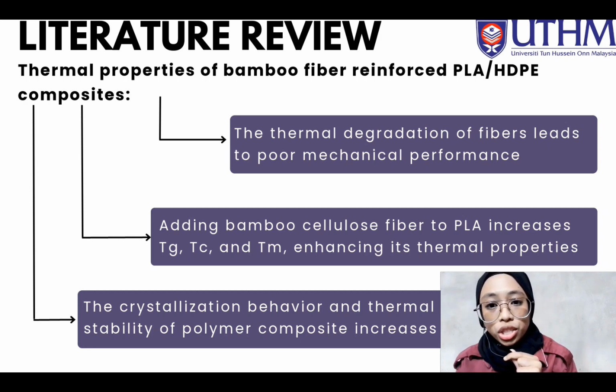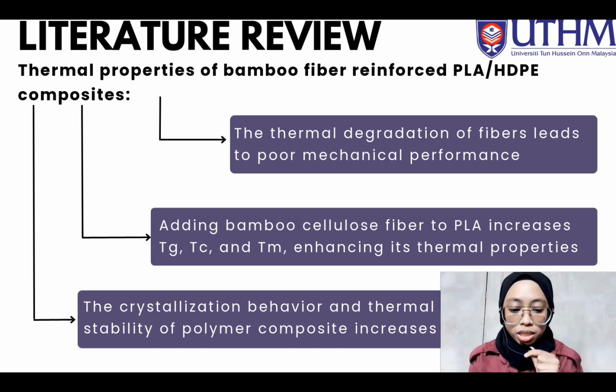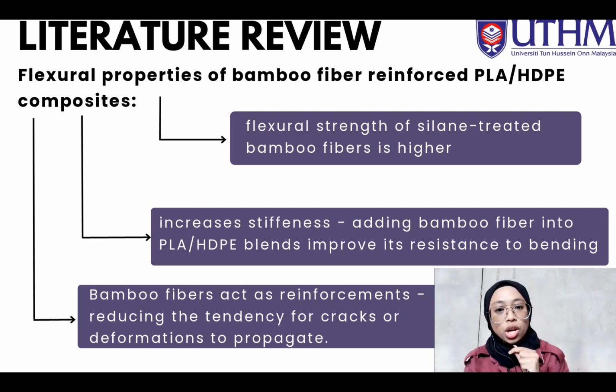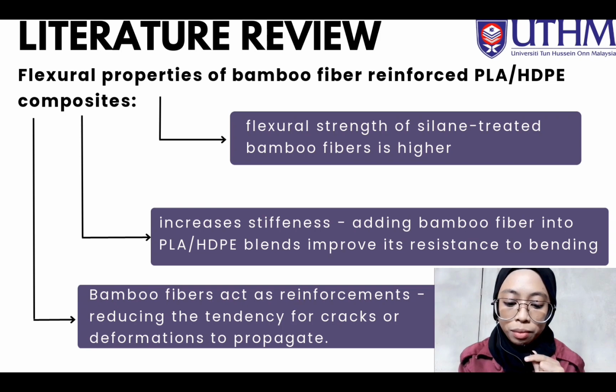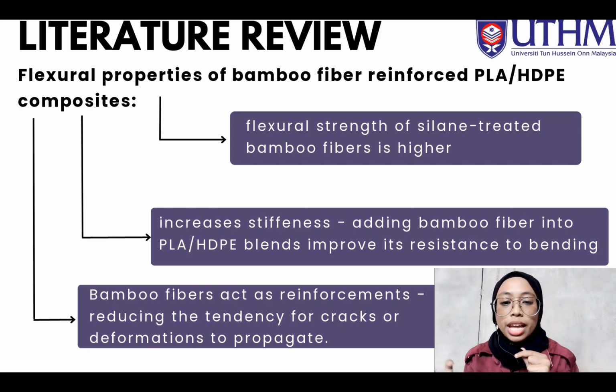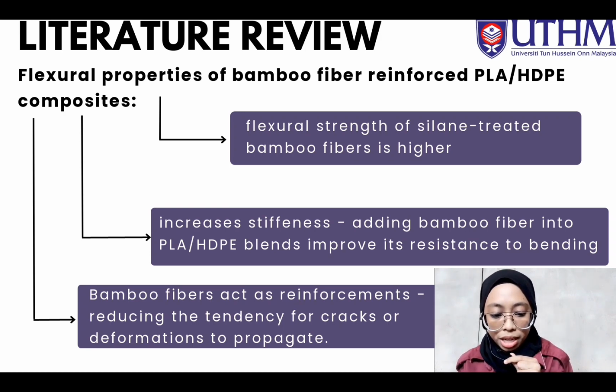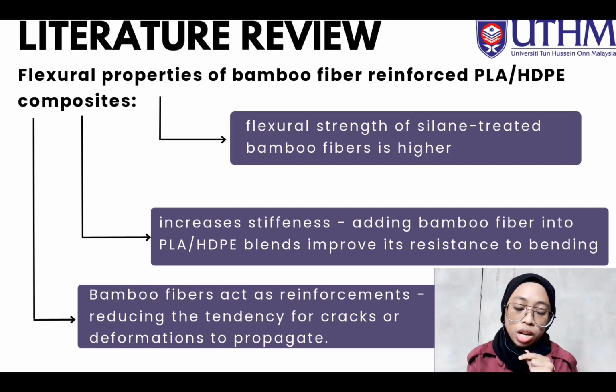Okay, next is about thermal properties of bamboo fiber reinforced PLA HDPE composite. The thermal degradation of fiber leads to poor mechanical performance. So, by adding bamboo cellulose fiber to PLA, it will increase the thermal properties of the composite, and also the crystallization behavior and thermal stability of the polymer composite increase. Next is about flexural properties of bamboo fiber reinforced PLA HDPE composite. The flexural strength of silane-treated bamboo fiber is higher. So when we add bamboo fiber to PLA and HDPE blends, it will improve the resistance to bending, the flexural bending, and it will lead to increased stiffness.